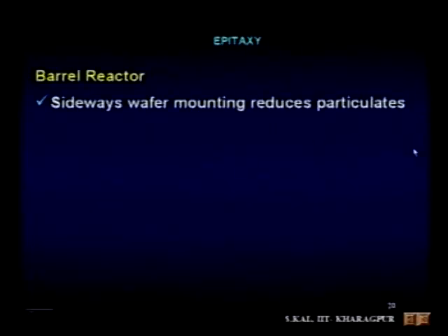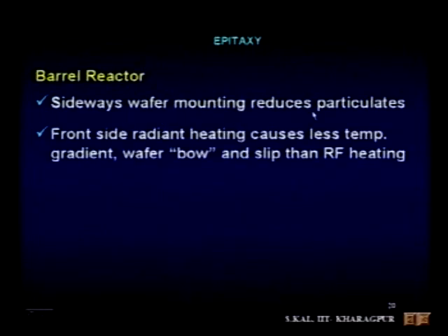Okay, so now the barrel reactor, why is it so popular? There are some points behind it. Sideways wafer mounting reduces particulates. This is one point. The wafers you are mounting on the sidewall, so if there is a shower of particles, they will not fall and stick on the surface, isn't it? In a horizontal reactor, the particles which are coming from the gas, or if there is a nucleation in the gas phase, those particles will fall on the substrate and will stick there.